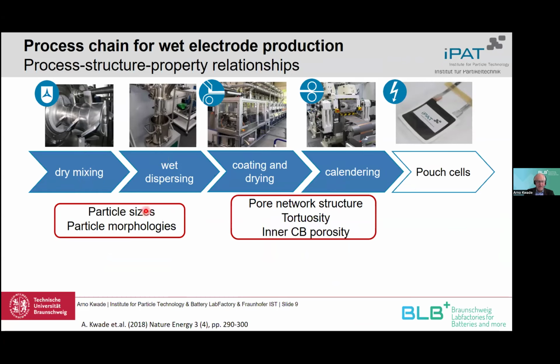First of all, for the dry powder mixing and also the wet suspension, at the end we can measure the particle sizes, the particle morphologies as a disperse parameter. And for the later electrode, we can measure the pore network structure, so pore size distribution, for example. We can determine the tortuosity. The tortuosity is the length of a path through your electrode for the ions. And this should be as short as possible.